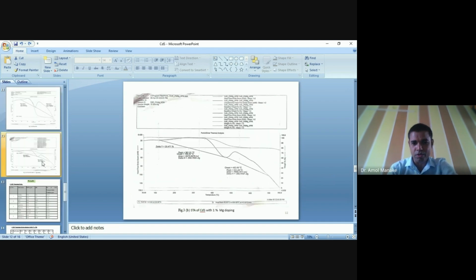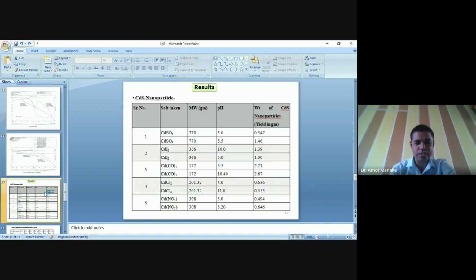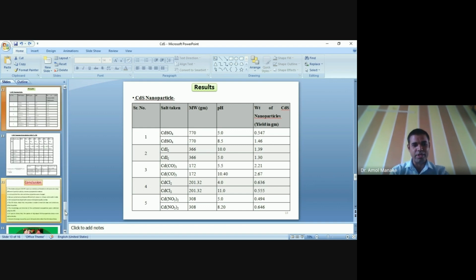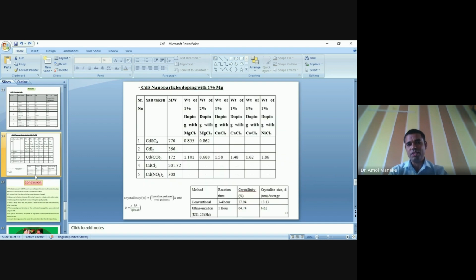This is the spectra of the cadmium sulfide nanoparticles with 1% Mg doping. Here is also only 20.47% of the weight loss. These are the various results, and these are the various salts we use: cadmium sulfate, cadmium iodide, cadmium carbonate, cadmium chloride, and cadmium nitrate. So many salts we use, and so much work is going on, sir, in the acidic as well as basic medium. The work is in progress.